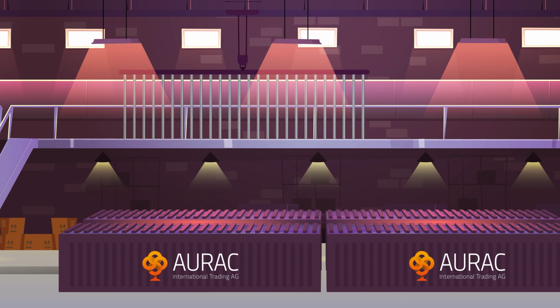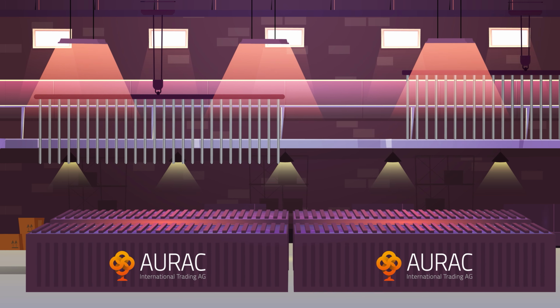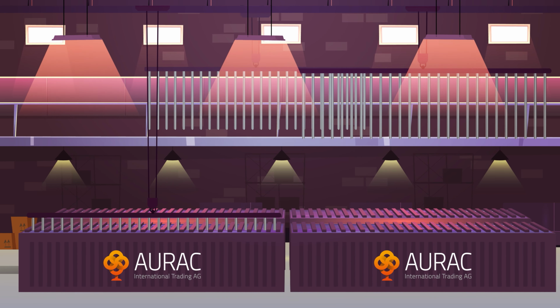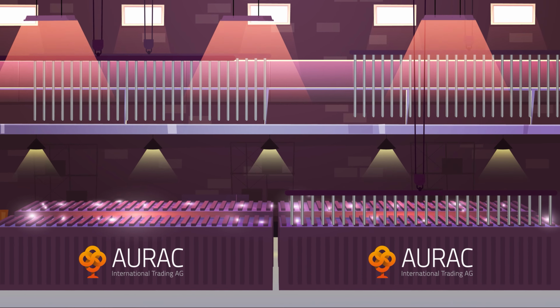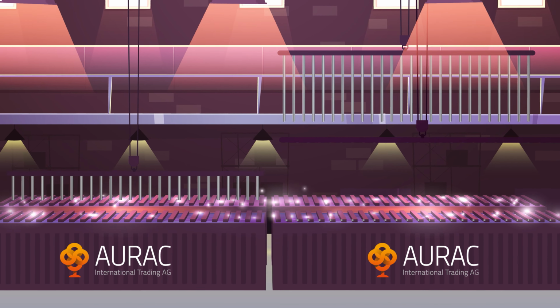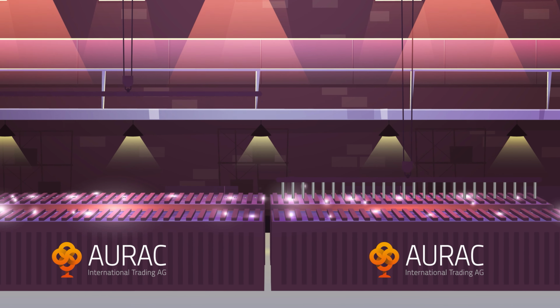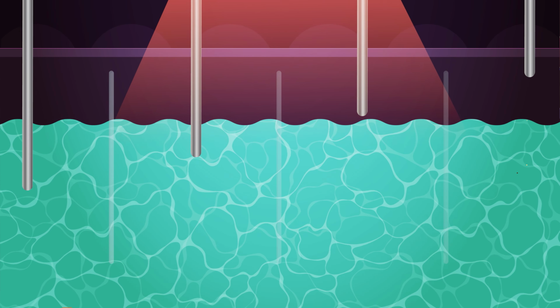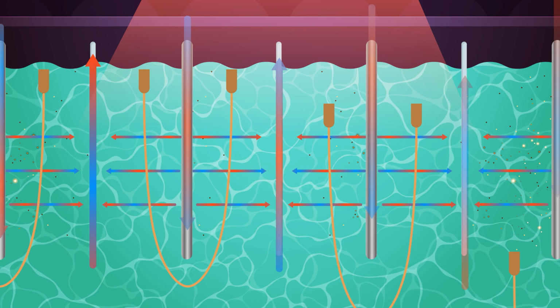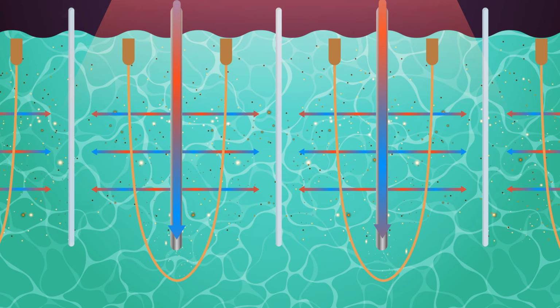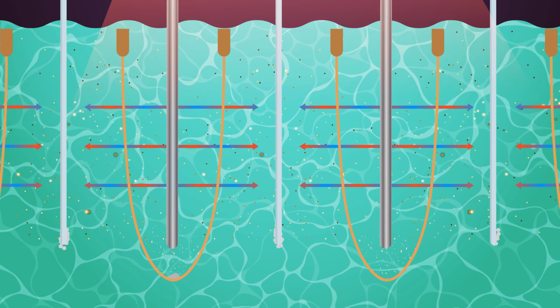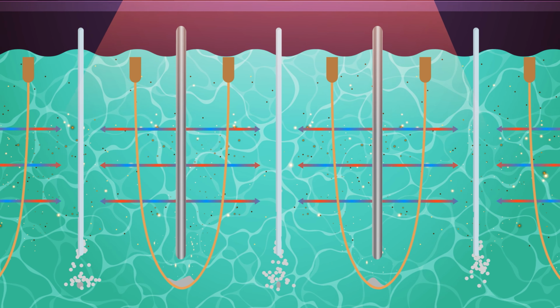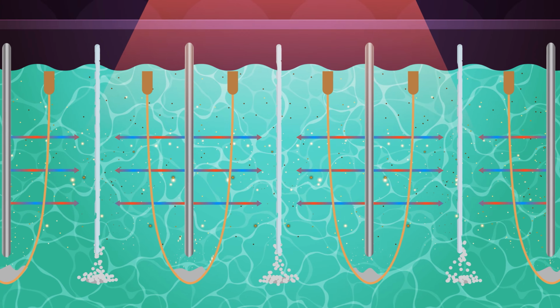This electrolysis process requires significant energy consumption. A low voltage of about 1 volt and a very high current of around 1,000 amperes are necessary to maximize silver deposition. The silver electrolysis process is unique because the precious metal plates are hung individually in bags, preventing impurities, like gold containing sludge, from mixing with the silver crystals.